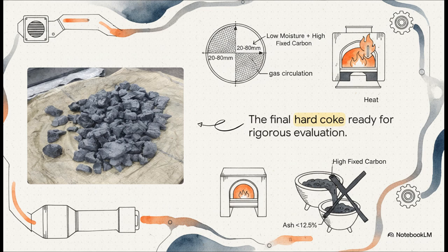We are looking for uniform sizing right in that sweet spot of 20 to 80 millimeters to ensure good gas circulation. We need low moisture, high fixed carbon for heat, and critically, we need that ash content to be as low as humanly possible, ideally below 12.5%, so we don't choke the furnace with slag.